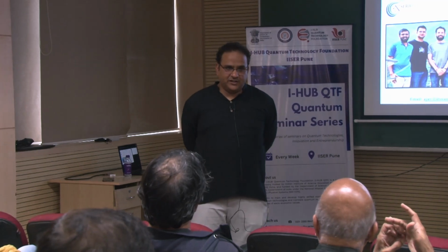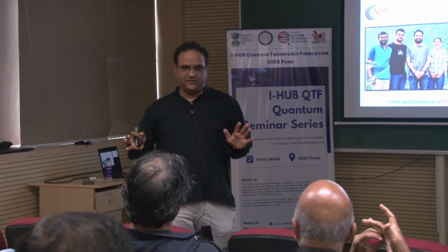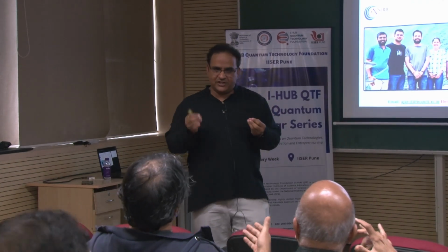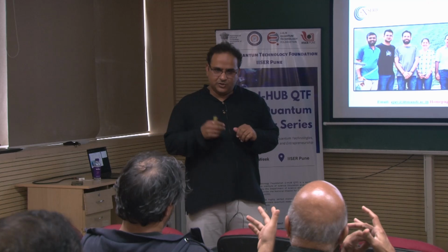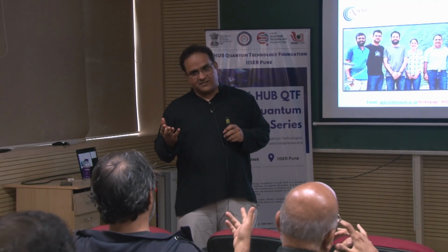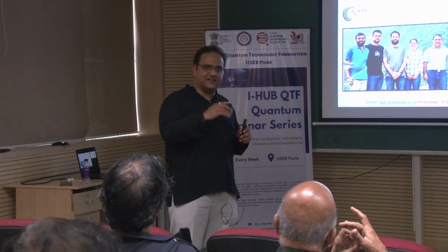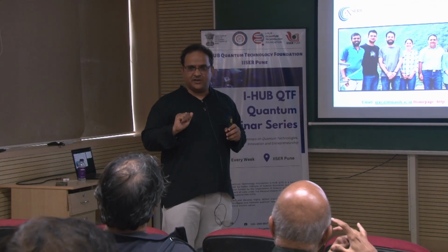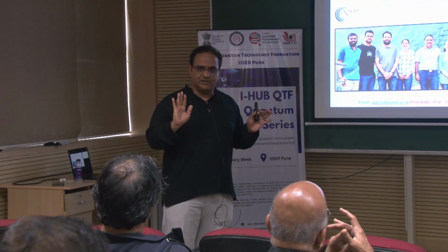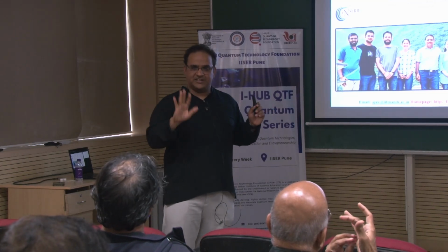Okay. First thing I wanted to clarify: don't get confused with that. It's just the doubling of the lattice parameter. It can be in between. The doubling of the parameter is just a simple model to explain charge density wave. A very special case is doubling. You can have irrational numbers. That's the incommensurate charge density wave, and most of these materials have the incommensurate charge density wave. A very limited number of materials show the commensurate charge density wave, and they will be more interesting to see using transmission electron microscopy at low temperature.